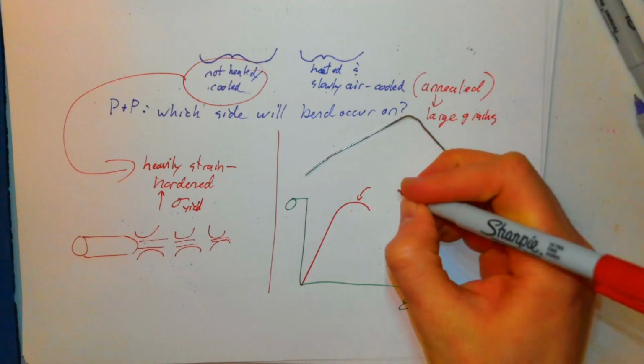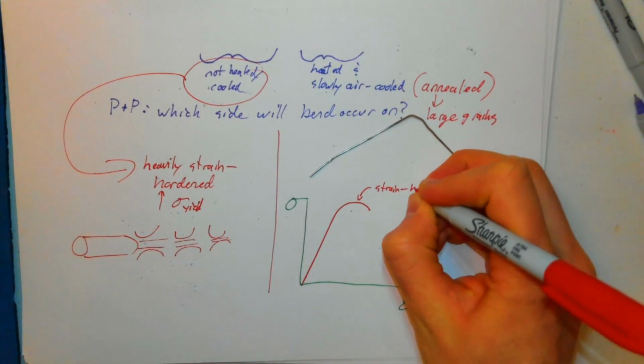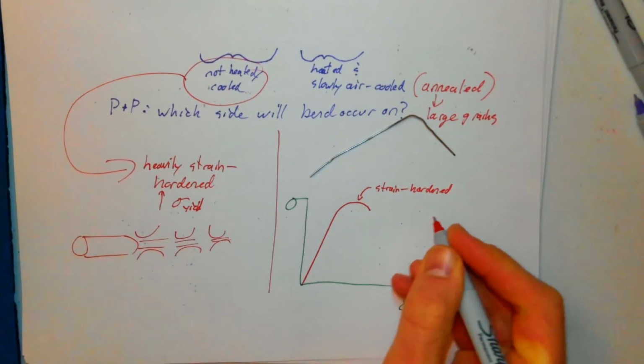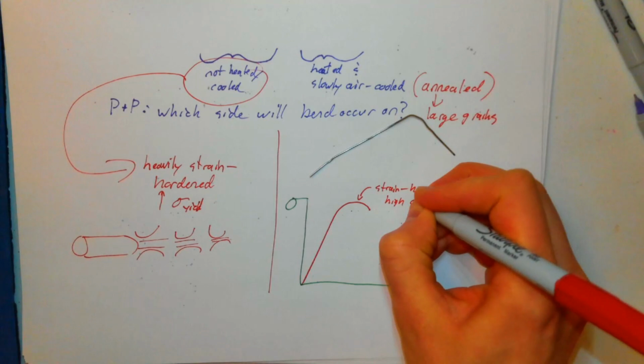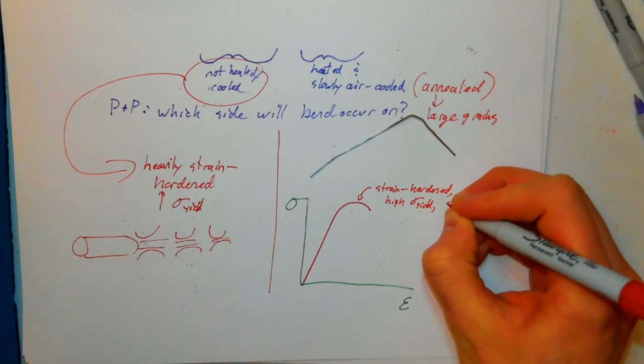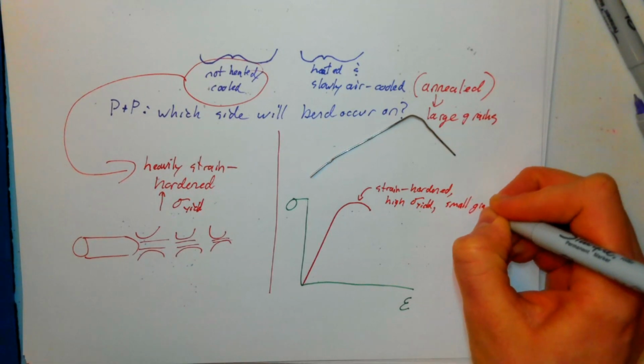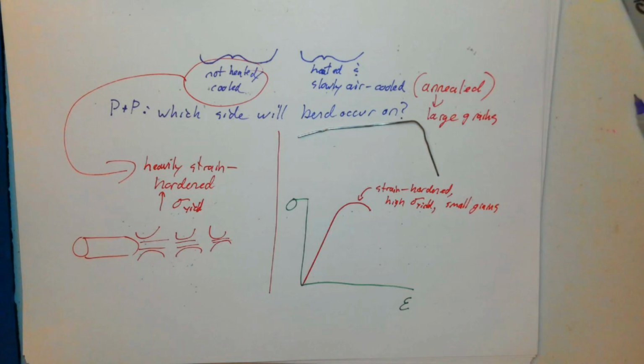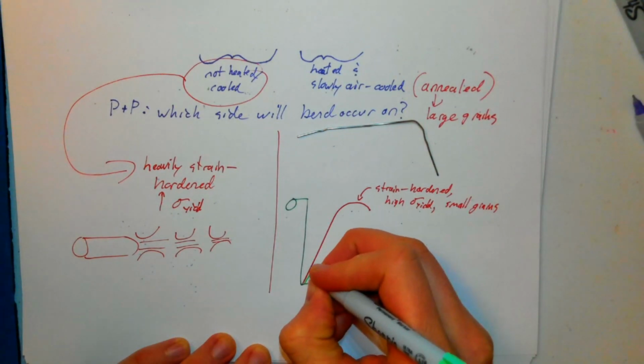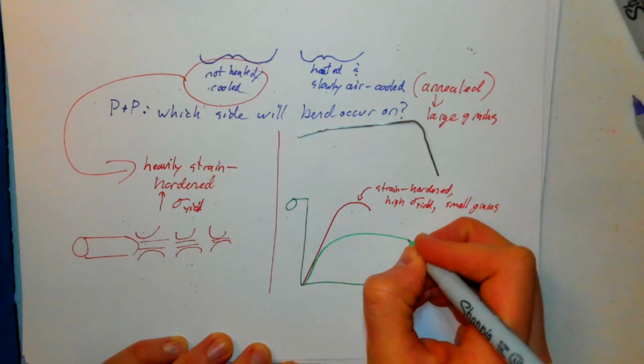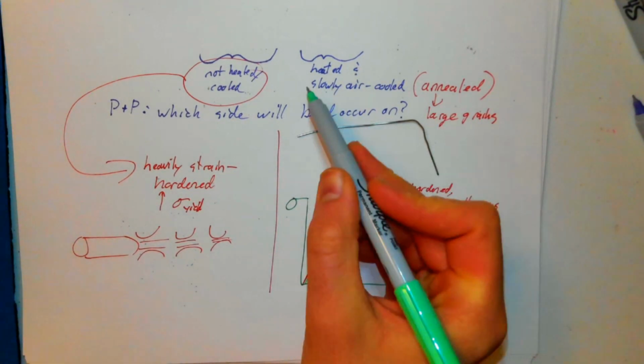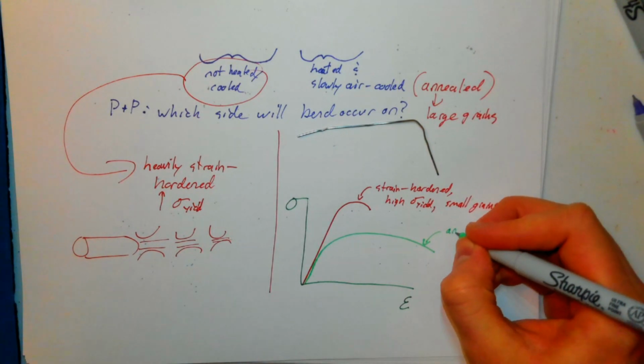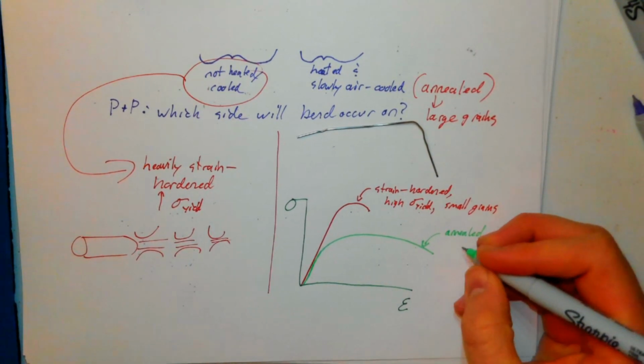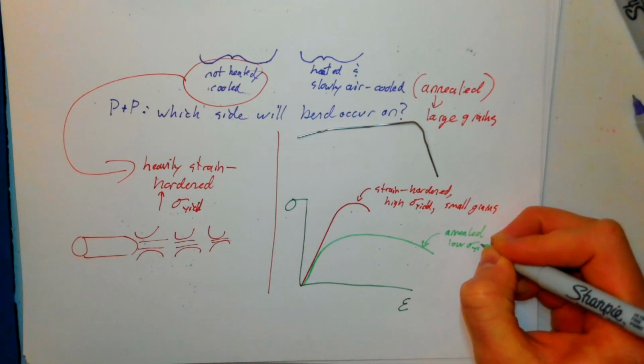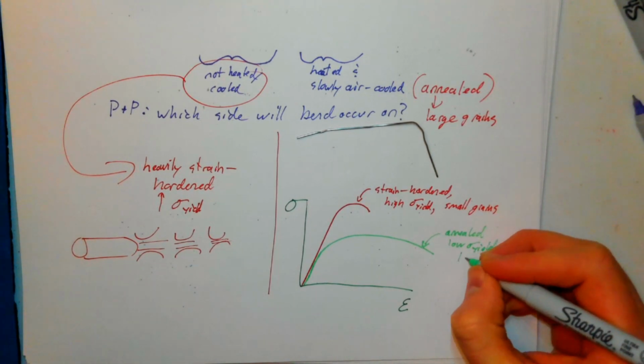So this is basically the strain hardened. The strain hardened has a high sigma yield, and it has small grains. But then this other side, right here, it has the same modulus of elasticity, but with the heat treating and slowly cooling, I would say this is annealed, and it basically has a low yield strength and large grains.